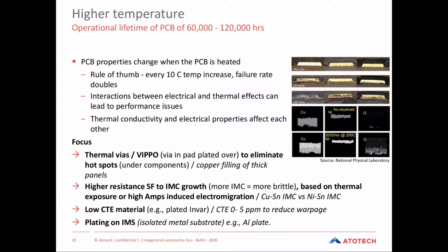So on the next slide, the effects of higher temperature. As a rule of thumb, every 10 degrees C temperature increase, the failure rate doubles. And this is really not what we want, and especially not in automotive. So to eliminate hotspots on our components and to shrink the BGA footprint on a PCB, VIPPO, via in pad plated over, is getting more and more attention, so the soldering pads can be placed directly under those hotspots. Typically, the through vias are conformal copper plated, then epoxy filled, grinded, and plated over again. That's where the name comes from.